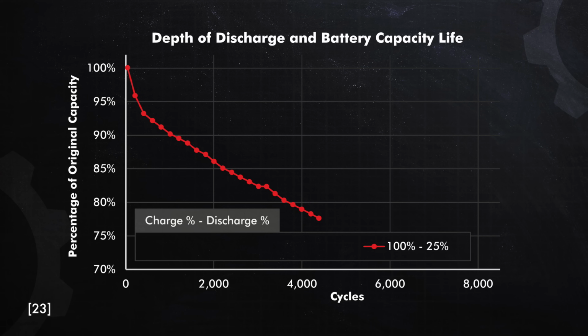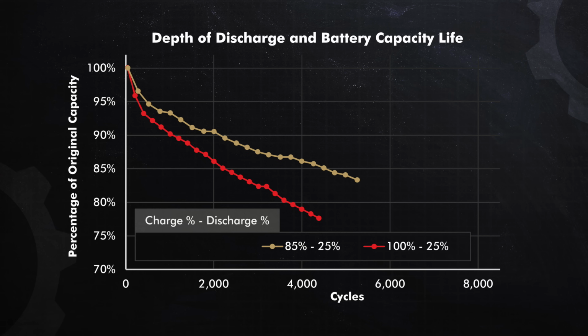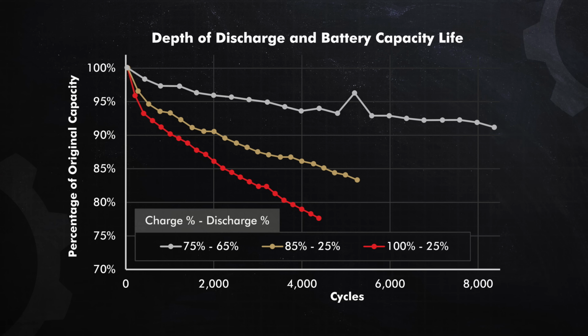In this data set here, we see that when a battery was drained from 100 to 25%, the capacity fell below 80% of its original value by 4,000 cycles. A depth of discharge between 85 and 25% performed better, but the best performance was for a depth of discharge between 75 and 65%. After 8,000 cycles, this battery has maintained more than 90% of its original capacity, which is